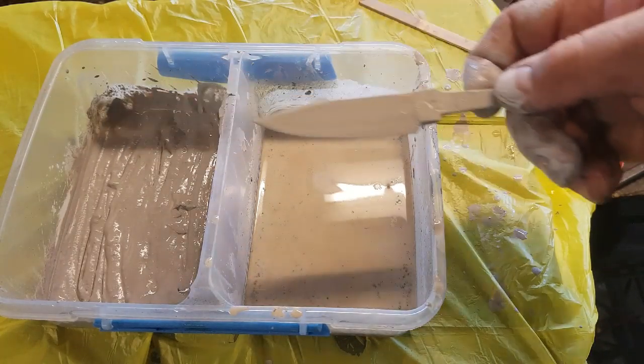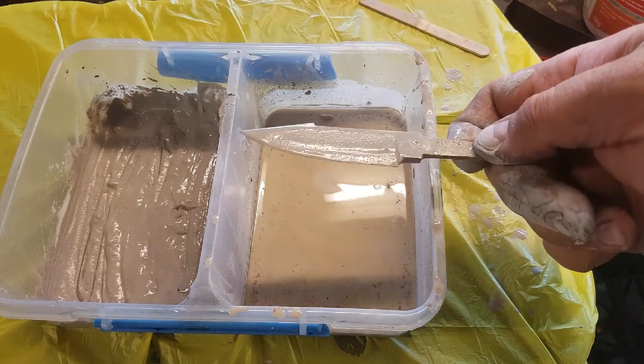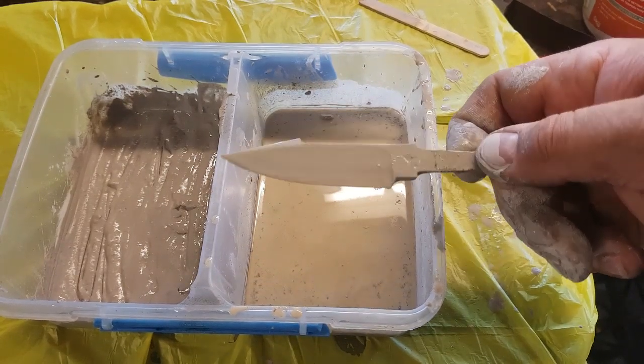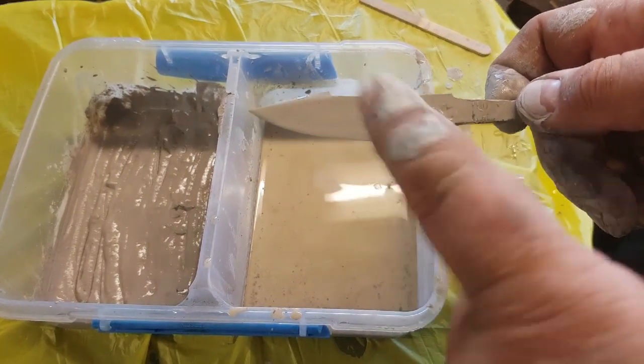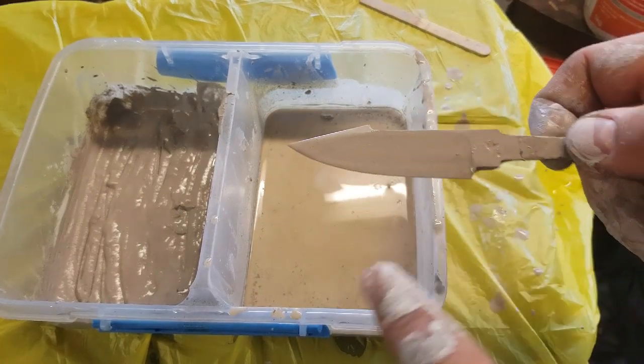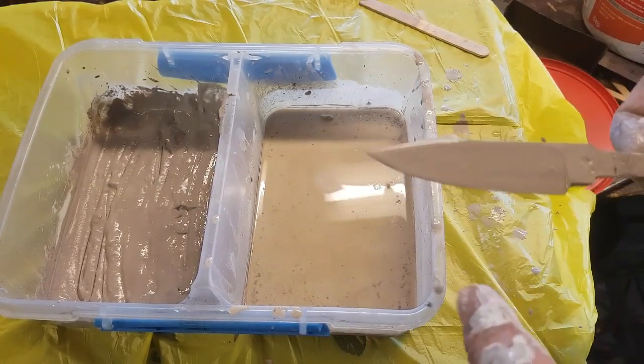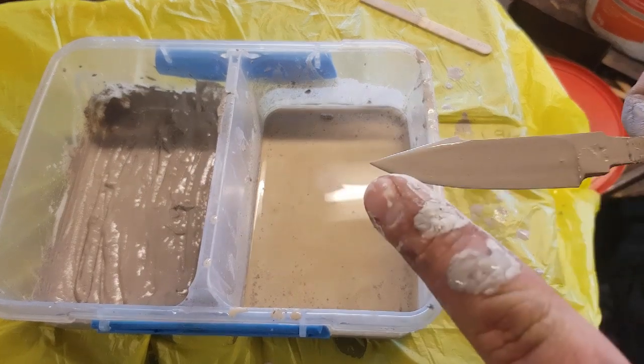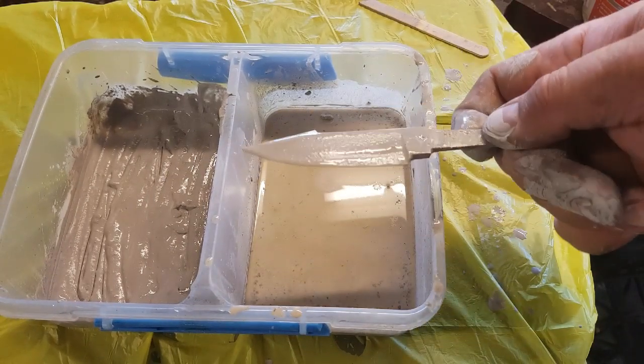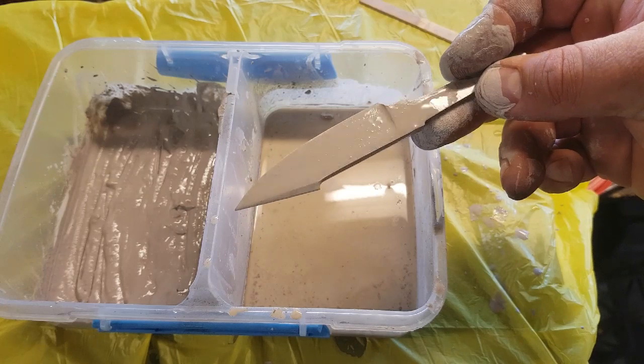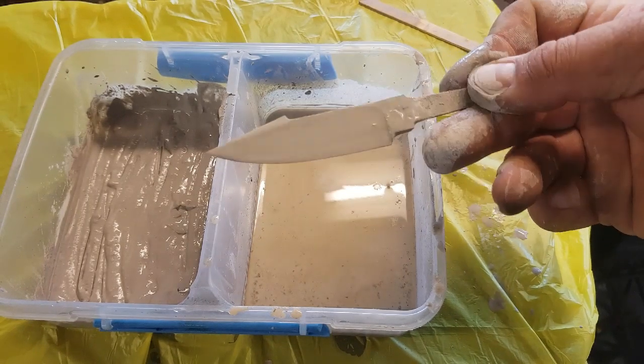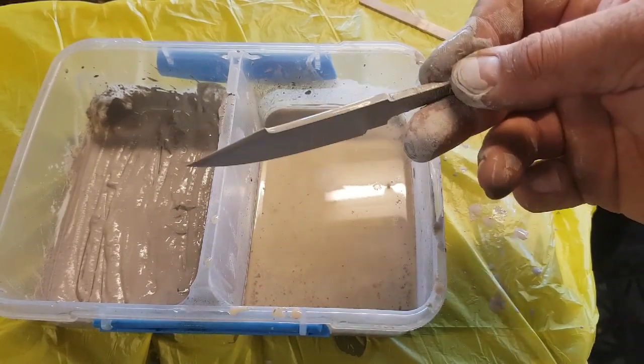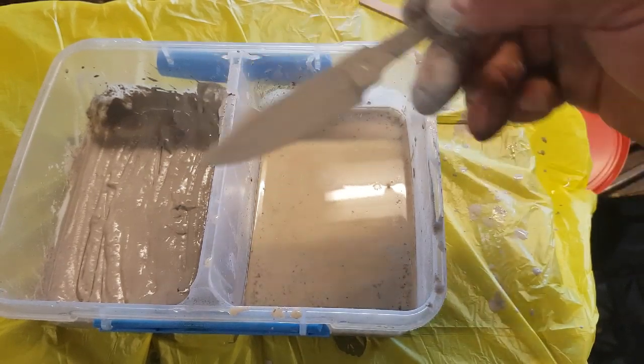What can happen is that the clay will shrink and you'll see cracks appear on your clay surface. If that happens, you need to reapply your layer of slip. You don't need to knock off the rest, but you just need to reapply to fill in those cracks, because you don't want bare metal being laid out. So I'll come back when this is dried out enough for me to apply the Hamon clay.